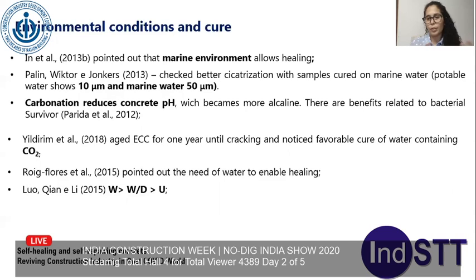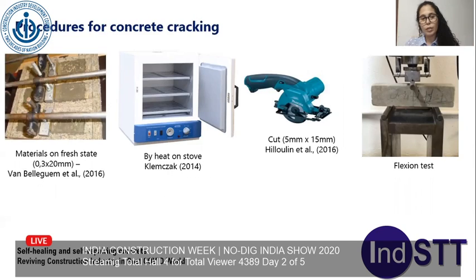We have procedures for concrete cracking: put materials in the fresh state, put the samples on the stove for the cracking formation by heat, cut the samples, or do the deflection test. And also to check if the healing and the repairing is working, we have chemical, physical, and image analysis.